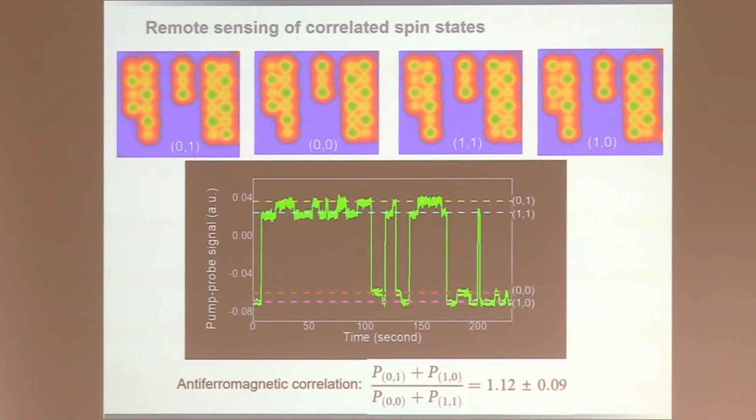So, thanks for the question. I tried to brush over it. So one part is, when we raise the temperature a bit, it switches on its own. The other part is, while you're measuring here, you're injecting electrons into the surface. And these electrons can actually travel over quite long distances and then induce switching on these structures. Despite the insulator? Despite the insulator, despite several nanometers distance. Here we didn't, but for other structures we can additionally use geometric frustration to limit the interaction, and it still is there.